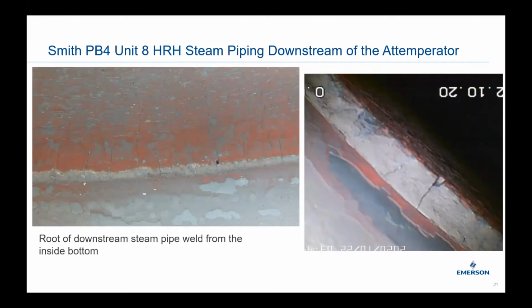When we did the NDE on this crack, they measured the depth at 0.685, and this is a 1-inch thick pipe, so that did cause some concern that this crack was starting to go through wall and could be a potential safety concern. So we did initiate projects to move forward and install this steam atomizing attemperator system at these two units as well at the Smith plant. So that's what these photos are showing, some of that crack.